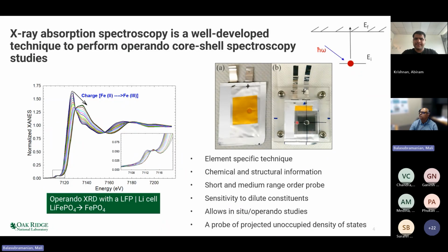And the beam goes through this beryllium window and the entire pouch as you're performing the X-ray absorption study. With X-ray absorption, you can get information about chemistry a little bit, like the oxidation state. For example, in this case, one can clearly see that this edge region of the X-ray absorption shifts to higher energy, and there are distinct changes in the so-called pre-edge region of the X-ray absorption.